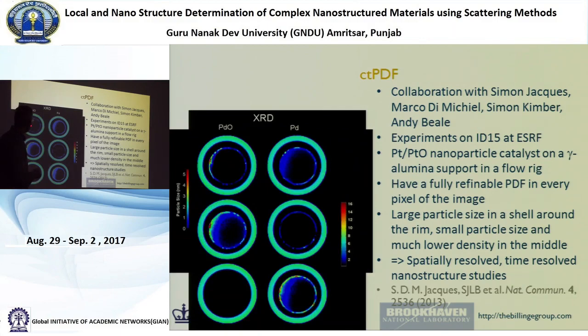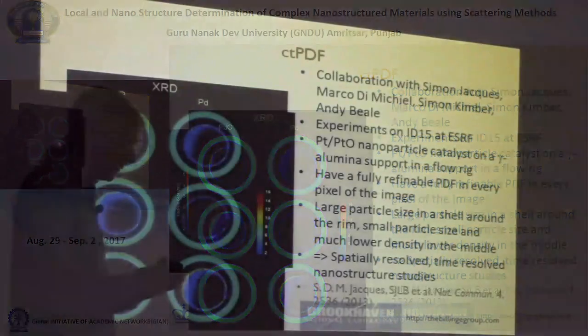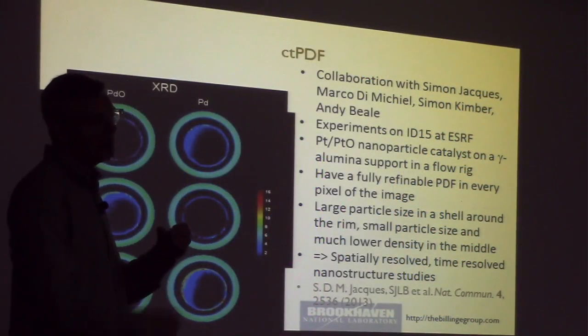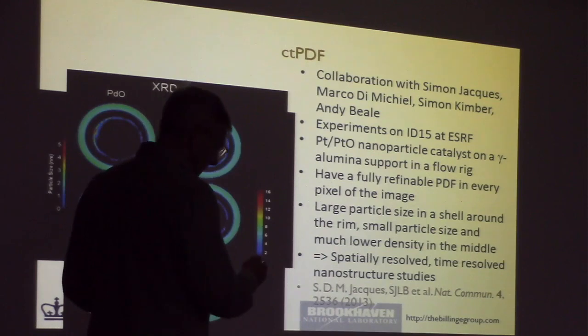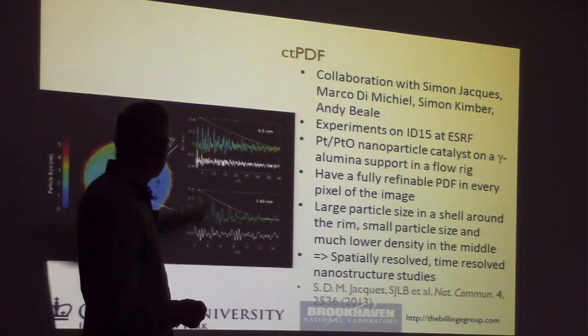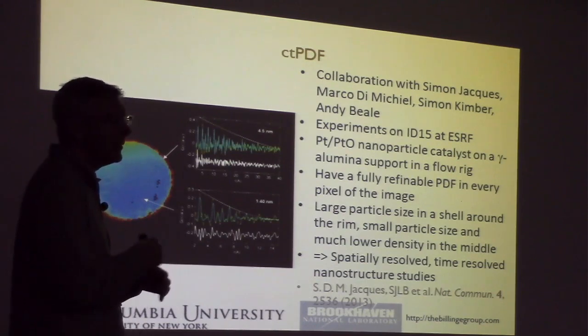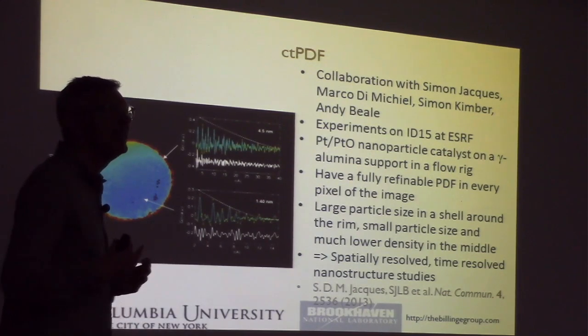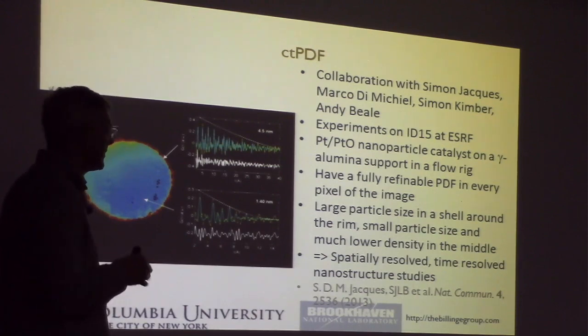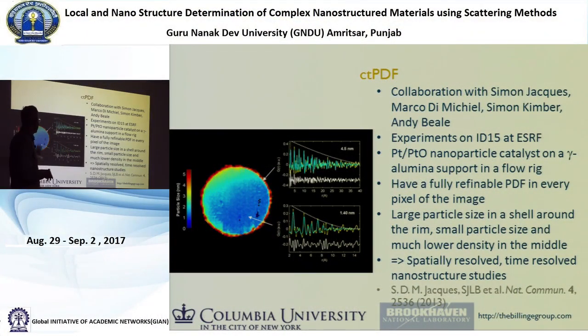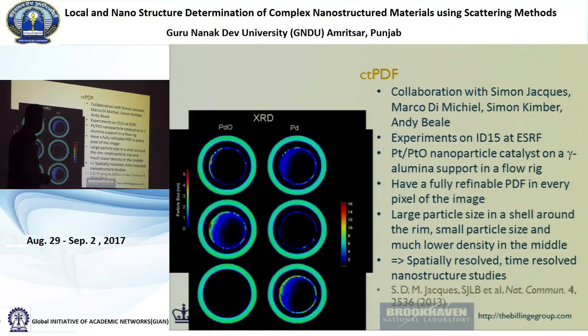So this is what it looked like. This is a catalyst body, and these catalysts were held inside thick glass tubes, so that we could pass gases over them. So we pass hydrogen to reduce it, and then oxygen to oxidize it. But when we did the measurement, there's no signal from the glass in any of these pixels. So even though there was a very thick container, the CT reconstruction, the tomographic reconstruction removes the signal from the container. So as long as the beam can get through okay, we can do measurements inside really nasty containers, and we get a nice clean signal without having to subtract the background, because the CT takes care of it. So this is actually the glass tube that this thing was sitting inside.